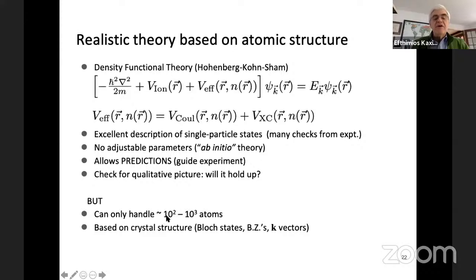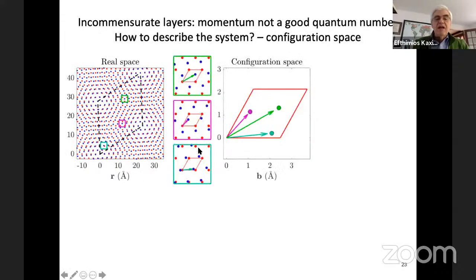The trouble is that you can only apply this when you have systems that contain about 100 or at most 1,000 atoms. And when you create these twisted layers, you have systems that contain in each periodic cell, large periodic cell, even hundreds of thousands or even millions of atoms. So you cannot apply these calculations directly in this case. You have to do something a little bit more clever. So we teamed up with a group of mathematicians who helped us visualize this and develop this better.